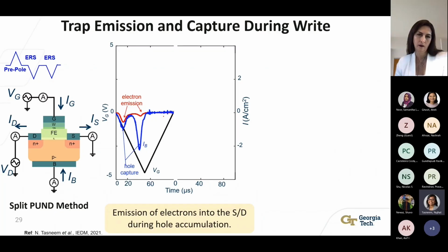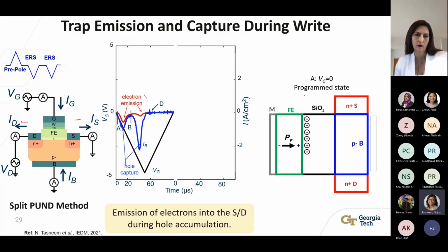However, what is interesting is that at the same time, we see a significant amount of electron current flowing through the source and drain that can be measured by the split PUND technique. Now, what does this mean? This means that initially, when the device is in programmed state and the ferroelectric is pointing towards the right, the majority of this polarization gets screened by trapped negative charges at the interface.